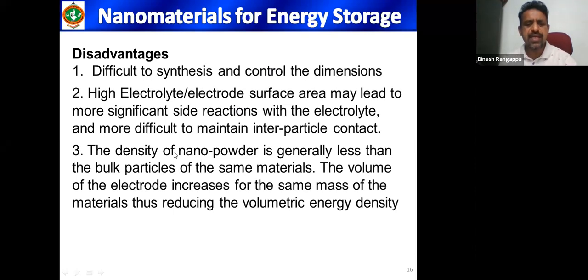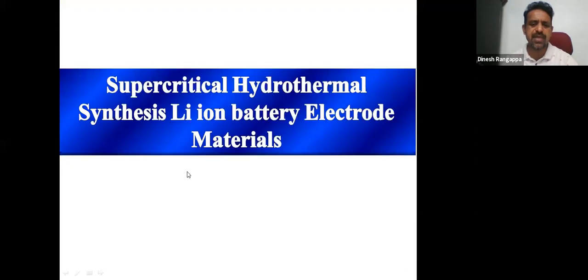and people are working to solve this one. And the density of nanopowder is generally less than bulk particles of the same material. The volume of electrode increases for the same mass of the material, thus reducing the volumetric energy density. Because of the lower powder density, the volumetric energy density will be reduced. That is another disadvantage with nanomaterials. But still, we have a lot of advantages with nanomaterials as electrode material, and people have exploited these advantages, and now many nanostructured materials are being used in lithium-ion battery electrodes.